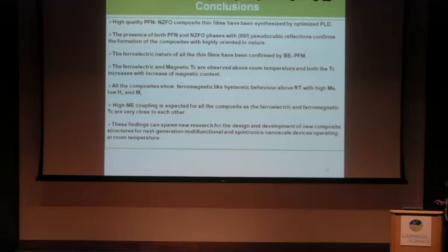The ferroelectric and magnetic transition temperatures TC are observed above room temperature, and both TC increase with increasing magnetic content. All the composites show ferromagnetic-like hysteretic behavior above room temperature with high saturation magnetization, and high magnetoelectric coupling is expected for all the composites as the ferroelectric and ferromagnetic TC are very close to each other.